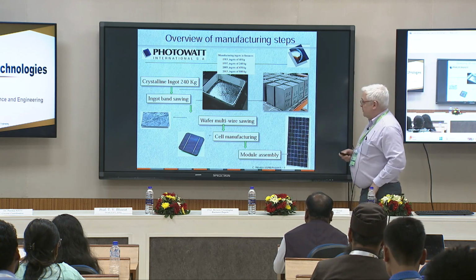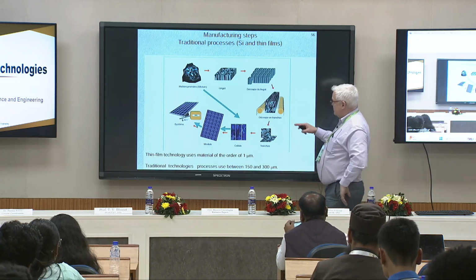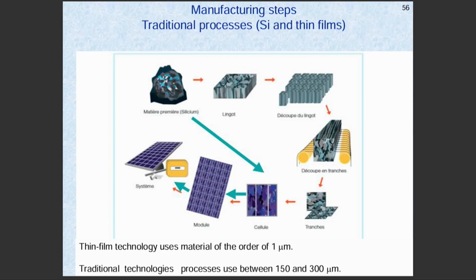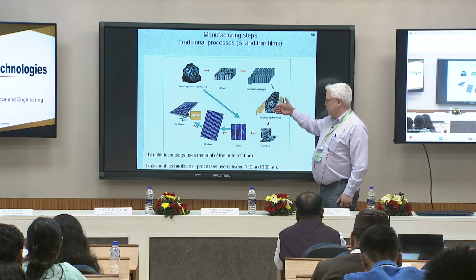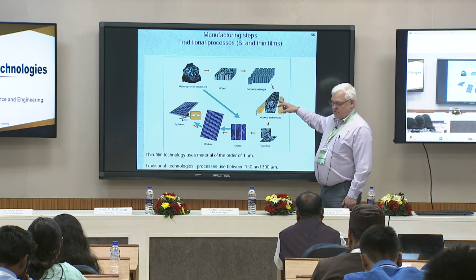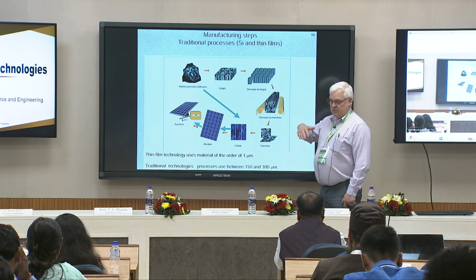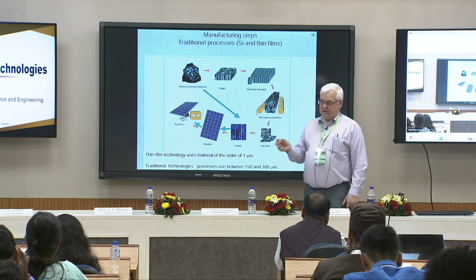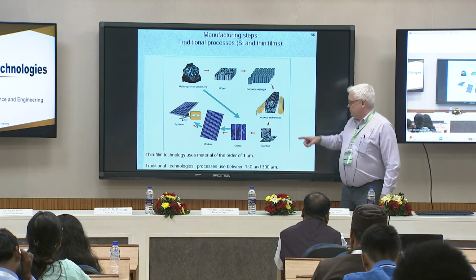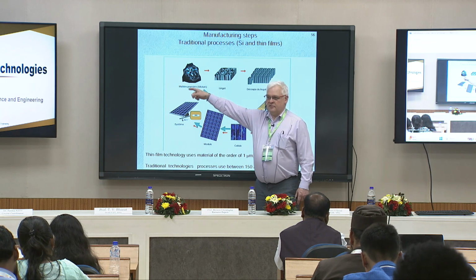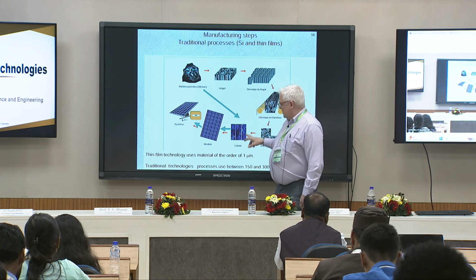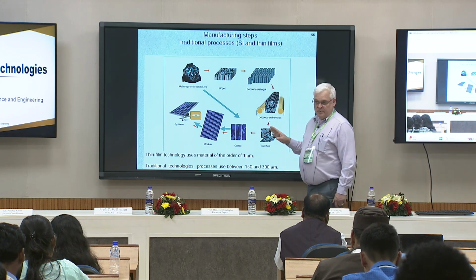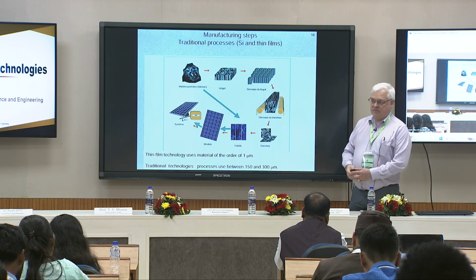One other important thing is that during this cutting process, the loss is very important. You can imagine it's very thin, and cutting 150 micrometers is very dangerous. So you have a loss at this stage of around 50%. Because if one of the cells is not perfect, there's a crack, there's a break. Then it returns at this stage. It can return until you have put on the PN treatment and the anti-reflective coating treatment.